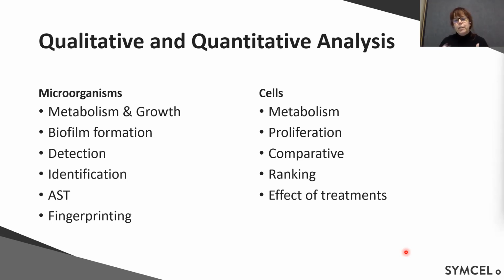And then if we look at cells, they don't grow or proliferate that fast. So usually when you're measuring on cells, you will get metabolic levels in your measurements instead. So even if you can't analyze this by number, you can do it comparatively. Like I mentioned, if there are diseased cells, how severe or what do they do depending on how much heat they put out. You can rank cells, or if you're going to produce a cell line, which is the optimal composition, and you can rank different compositions of the media to see which gets the best activity, if that's what you're looking for. And you can look at the effect of treatments.